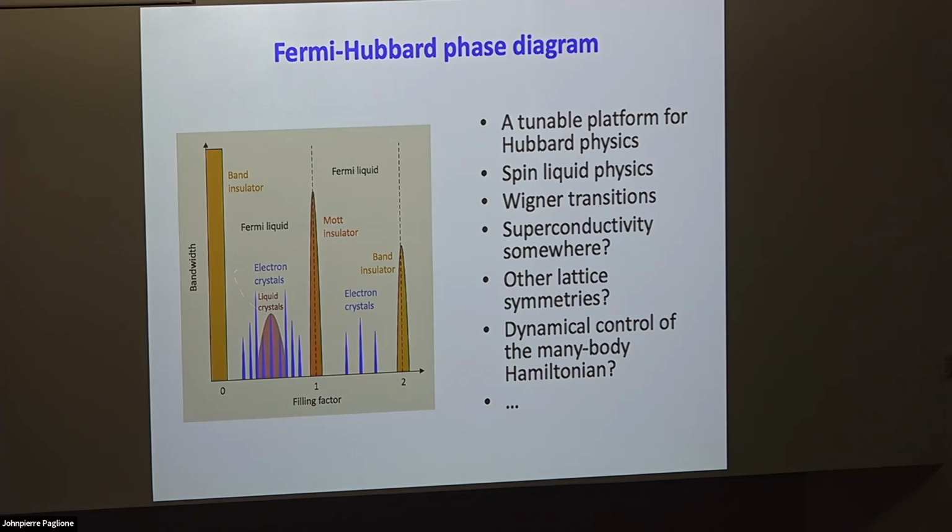Then I would call it an electron crystal. But if you increase the bandwidth, the electrons, due to quantum mechanical effects, start to become more delocalized, and the electronic charge density wouldn't be 100% modulated from side to side. For an electron crystal, it should be 100% modulation. Near the metal-insulator transition, as you increase the bandwidth, the electrons start overlapping in the wave function.